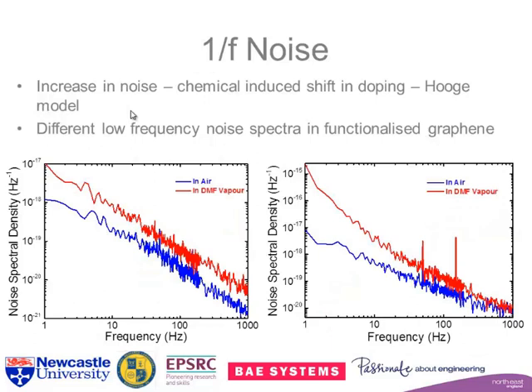To try and understand this a little better, we use 1/f noise, because this is quite a sensitive way of looking at the behavior of our layer. So here is the noise. When we add a chemical to the top, we've changed the doping density in the layer. According to the Hooge model, that explains that we should see a shift in the noise, which we do. So we're happy with that. This one then is the functionalized one. Again, we see an increase in noise here at moderate frequency. These spikes are UK mains, they're 50 Hertz, and we tried to cut them out, and it doesn't always work.